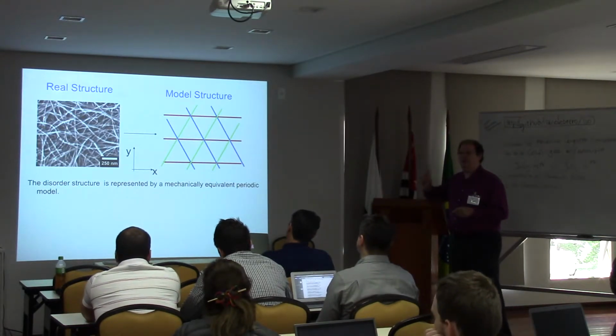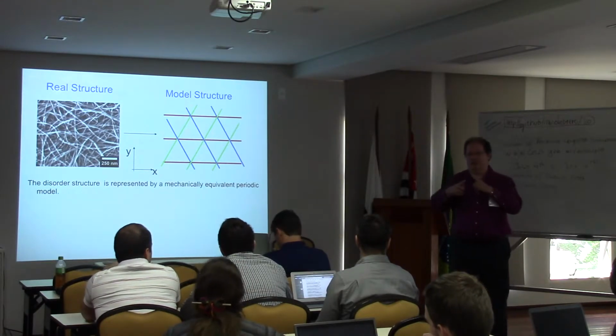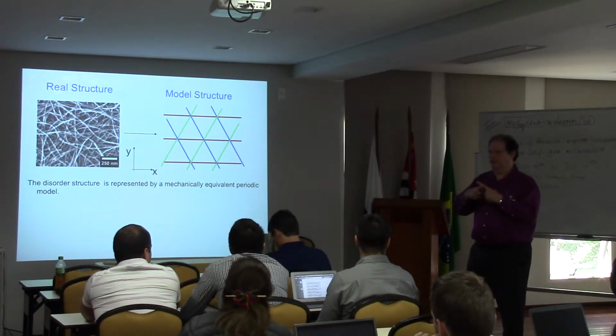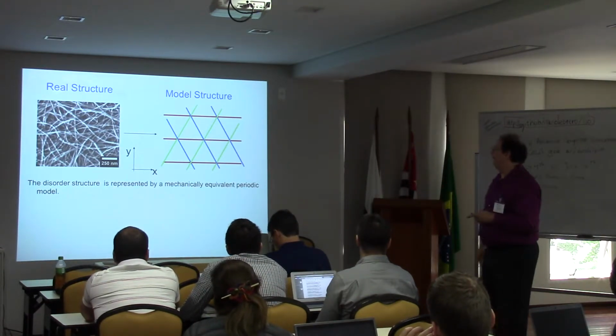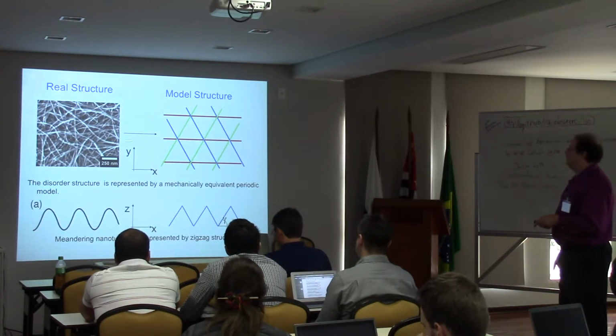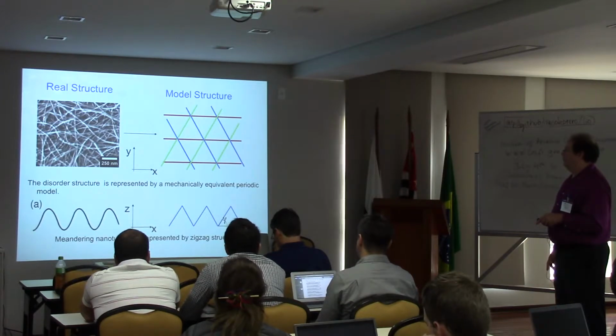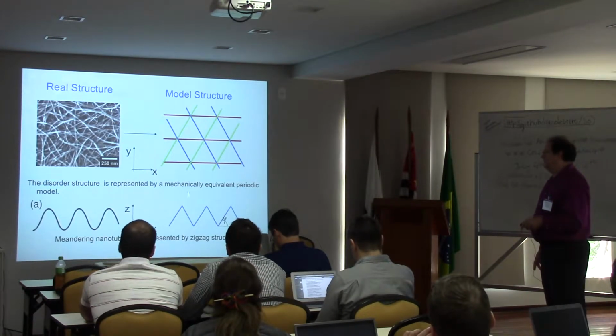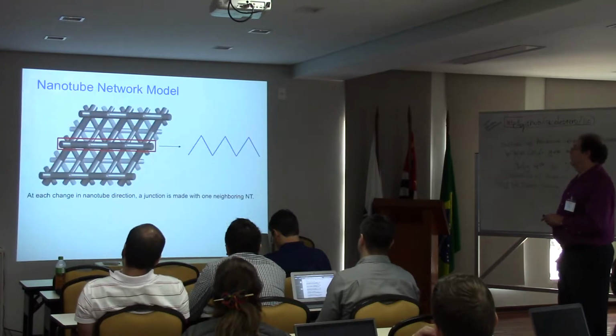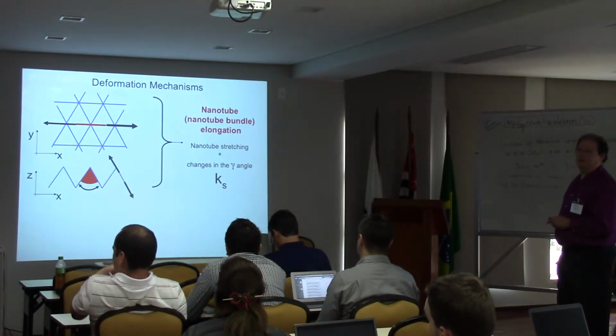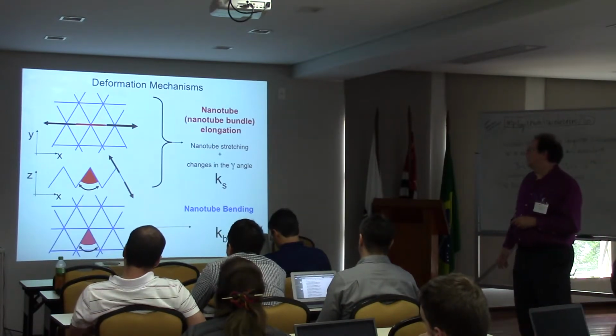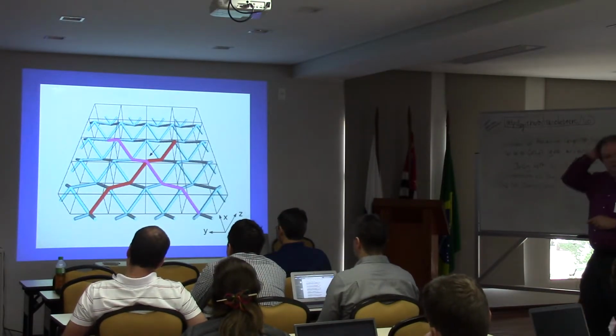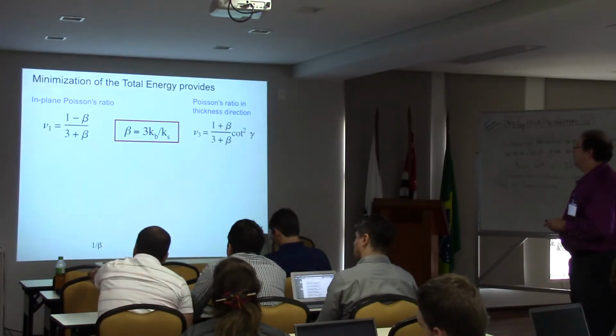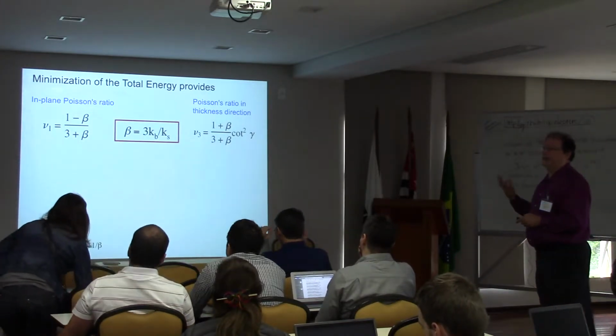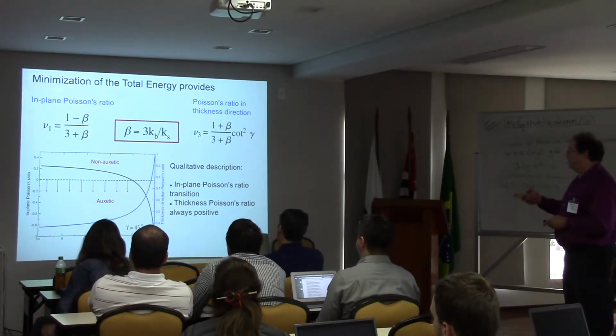From the behavior of auxetic materials, we know that the most important contributions are from bending and stretching. Your model has to reliably describe these two features. Okay? Then we simplify the model. Instead of using this complex structure, I use this approximate model with straight segments instead of the wavy ones, and try the deformation mechanism. After trial and error for 2 years, we got this structure. This structure reproduces the auxetic behavior. We can test this by deriving analytical expressions to estimate the Poisson ratio. It predicts the transition from non-auxetic to auxetic behavior.